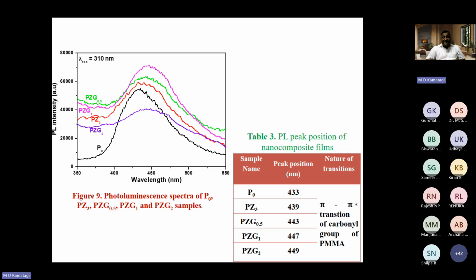Now this is the photoluminescence intensity as a function of wavelength. The peak position of pure polymer, that is PMMA, is 433. That of polymer and metal oxide nanoparticle is shifted towards the right side, that is 439. Then when we dope with the graphene oxide, this PZG composite with graphene oxide, the peak position has changed.